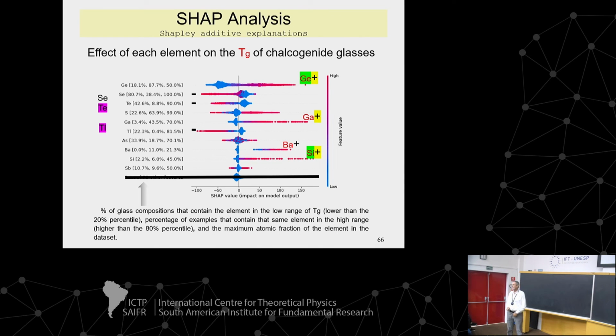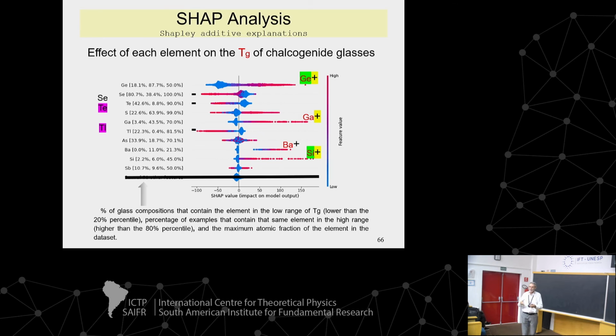Do a training, get whatever we have in the literature for the properties that have been measured by somebody, and then you do what's called a SHAP analysis. It's another algorithm that analyzes the models generated by the machine learning training. And this is a nice result. You see the TG again, because this is an important property. See, if I want to design a glass with high TG, red is high, blue is low. So a high amount of germanium, or gallium, or barium, or silicon will give a glass with high TG, a chalcogenide glass with high TG.